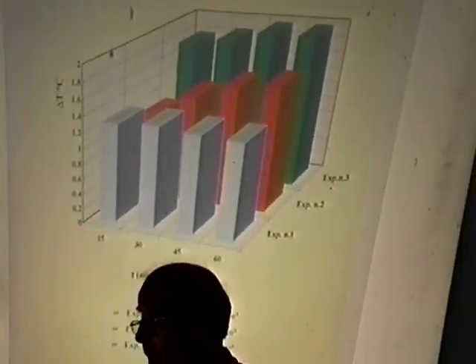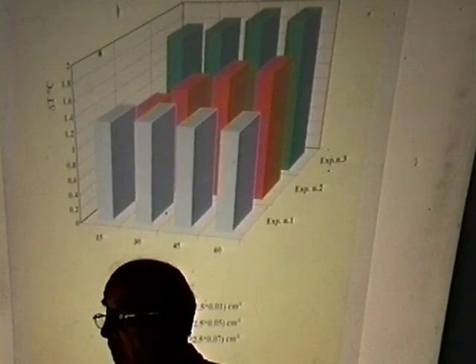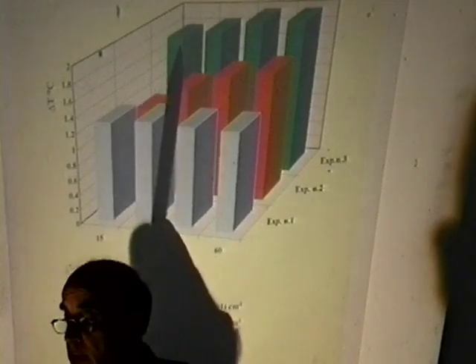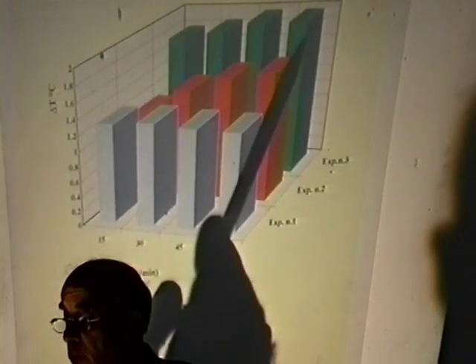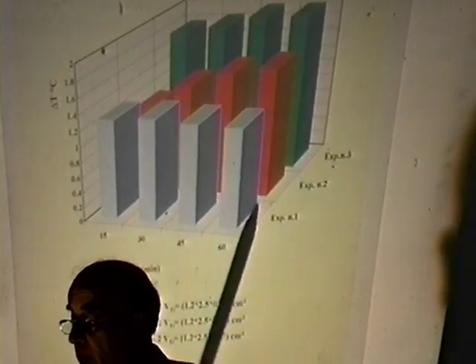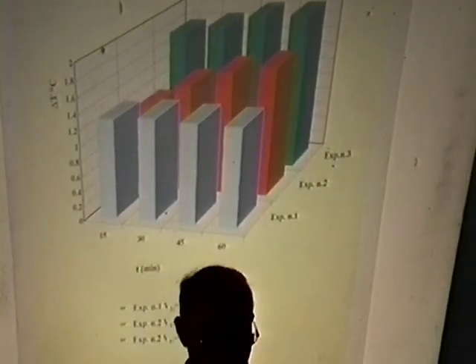This effect could be reproduced with other samples of the same batch. Here we are relating to the first hour of the after effect. This is the experiment which I have described before, and these are experiments with thinner samples. I have also to say that with this same batch of titanium, the effect was observed also with light water.